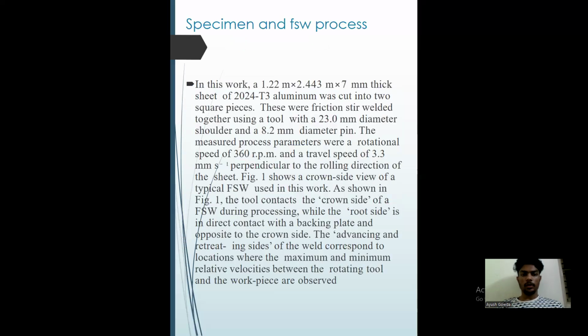In this work, a 1.22 m by 2.44 m by 7 mm thick sheet of 2024-T351 aluminum was cut into two square pieces. These were friction stir welded together using a tool with a 23.0 mm diameter shoulder and 8.2 mm diameter pin. The measured process parameters were a rotational speed of 360 rpm and a travel speed of 3.3 mm per second, perpendicular to the rolling direction of the sheet.